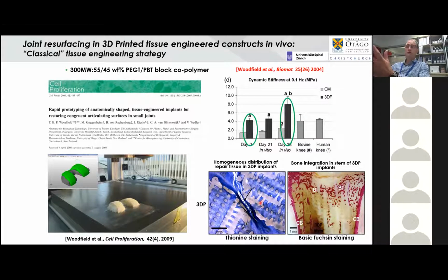Unfortunately, well, not unfortunately, of course, it's an extremely aggressive environment. You can imagine in terms of us being able to perform an osteotomy of the femoral component in this in vivo model and replace it essentially with a fully engineered construct. The remodeling process meant that we lost some of the hyaline cartilage that we had originally engineered. We still were able to maintain an articular surface, but the reason that I'm trying to give this example is that that was the latest technology at the time to be able to try and have an anatomical structure deliver autologous cells that have been pre-engineered to try and look at joint resurfacing.